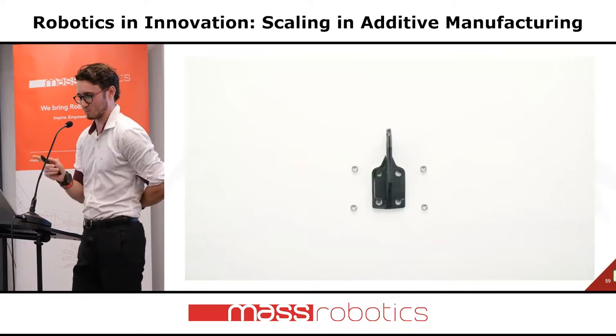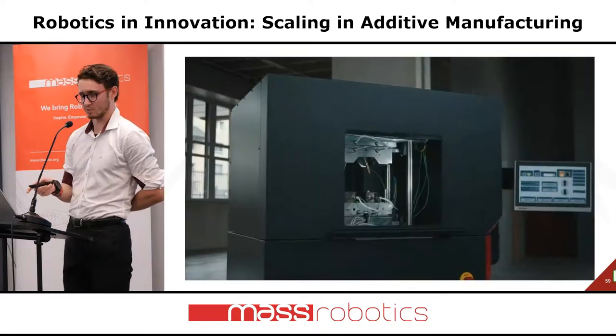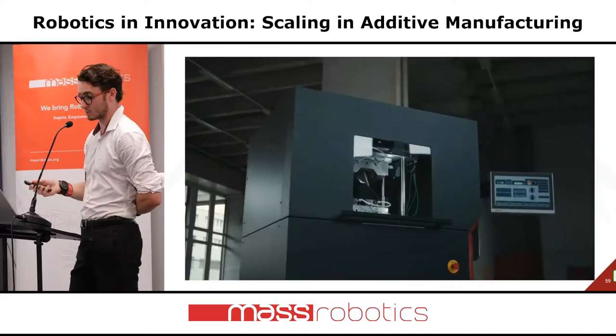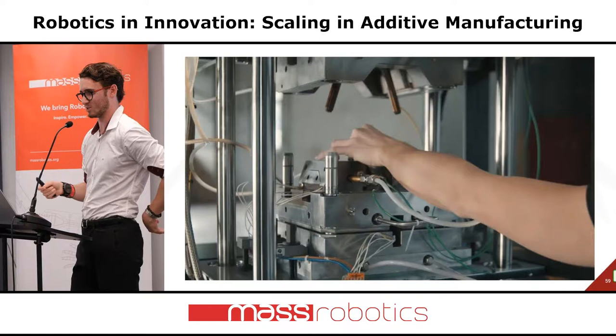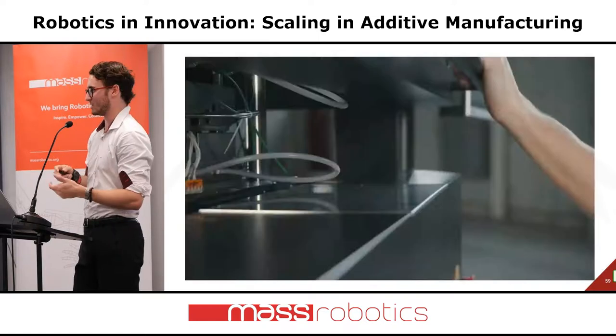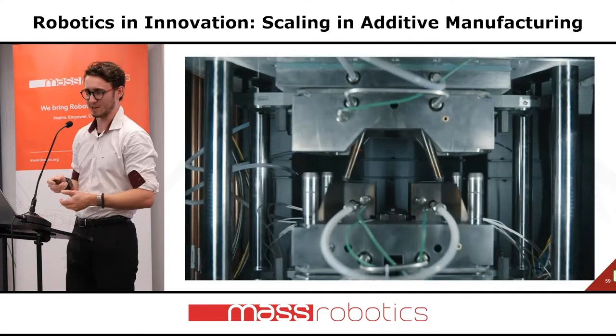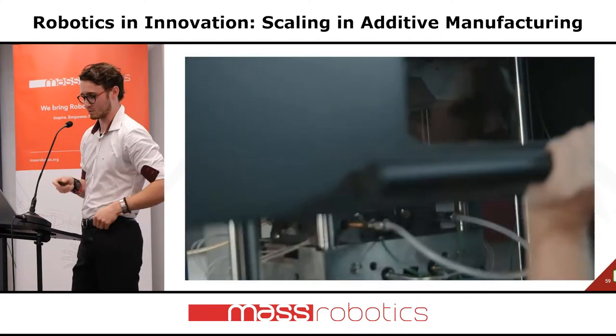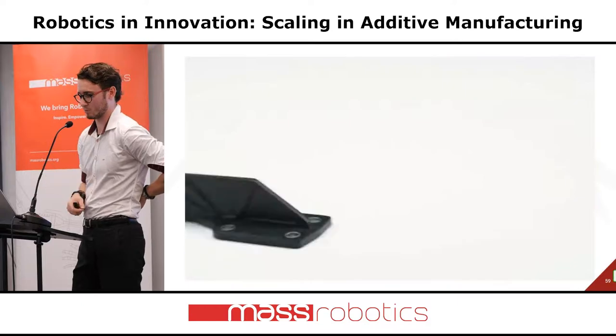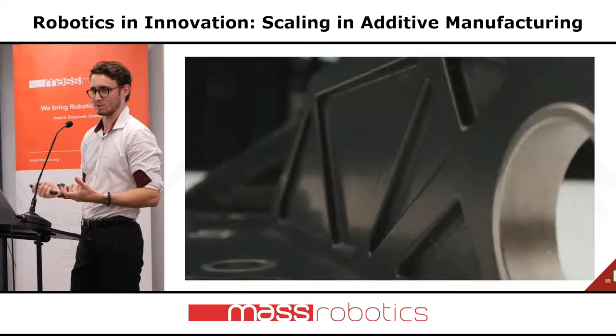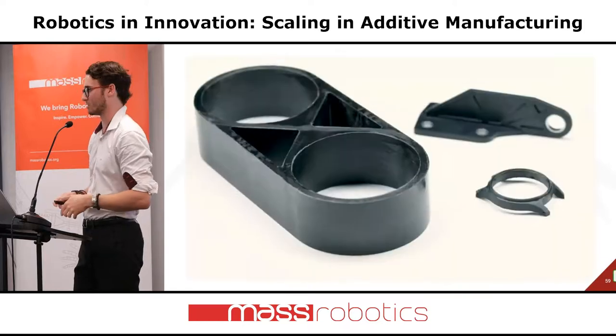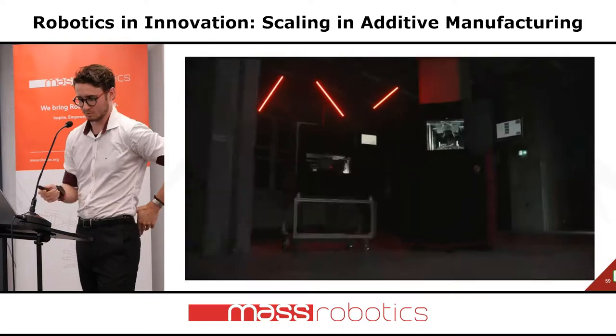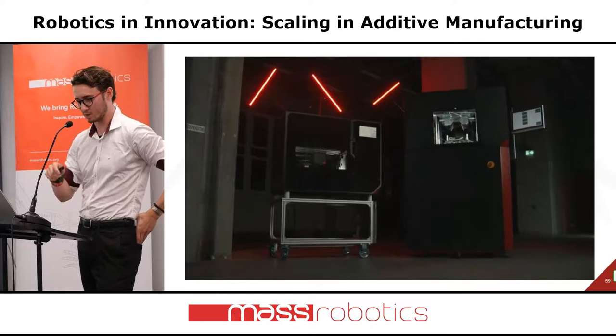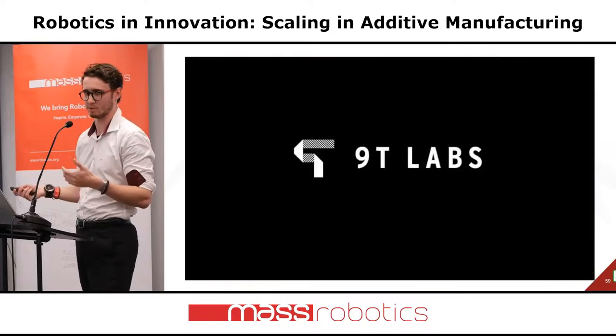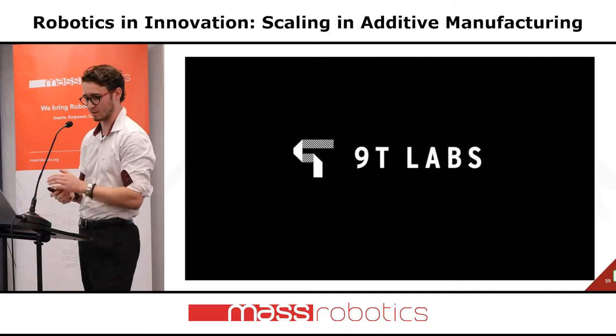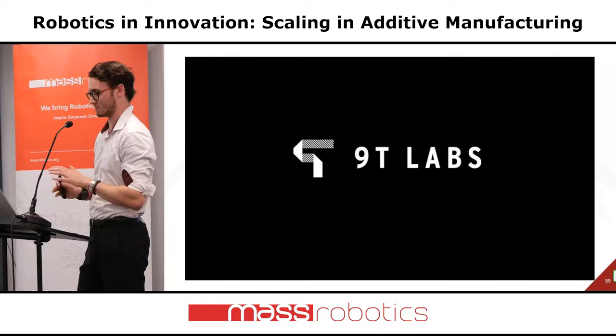So for this case, we print multiple parts. We also have these metal inserts, so just bushings, but they could be threaded inserts or anything, and those are molded right in. It's not like the soldering iron into ABS or PLA. You really can't do that at all with this type of material anyway, so they really need to be molded in, and the polymer shrinks around that. And there's a lot of industry kind of experience there as well, so we just tap into that. So that's kind of the solution where we have the printing to make these tailored preforms, and then we have the fusion compression molding to get rid of all the surface anomalies and get rid of everything.